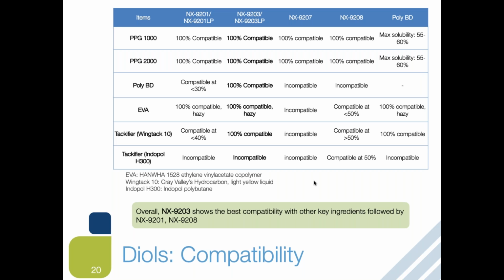As a formulator, as you know, you never use just one type of polyol or diol in your system. Therefore, achieving good compatibility with the various ingredients is quite important. So in this case, we have studied the compatibility with other diols like PPG-based, poly-BD, and other additives, ethylene vinyl acetate, or hydrocarbons. From this study, NX9203 has shown the best compatibility, 100% compatible with the polyether polyols and poly-BD and EVA and tackifier.